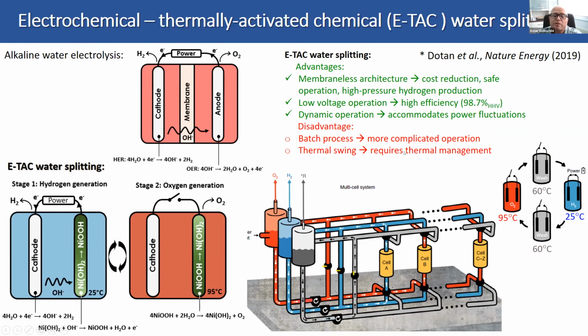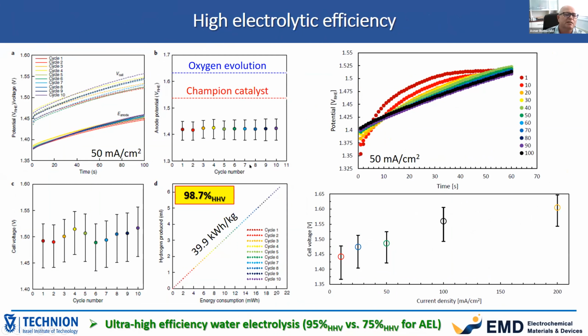So essentially, we replace complexity at the cell level, and more so at the electrode level, with complexity at the system level. So there's a completely different game here. Now, to show you our proof of concept result, here you see 10 cycles, and you can see that the anode potential during charging does not change, and it is kept on average at a low potential of about 1.4 volt, which enables us to do complete water splitting at a cell voltage of about 1.5 volt for these 10 cycles, which gives us very high efficiency, nearly 99% efficiency based on the hydrogen evolution, on the higher heating value.